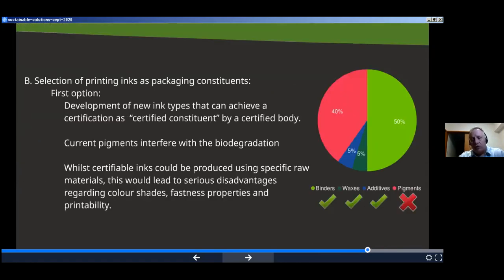One option is to change all the components of the ink to make them biodegradable. And here in this graph, you can see more or less the typical composition of the ink, where 50% of the ink is made of binder, which is a resin, typically. Then we have some waxes, additives, and then pigments. I told you before that the pigments are not biodegradable. So we can change these pigments into biodegradable pigments, like organic pigments, but we will never get the same color strength, the same light fastness, the same printing properties as current pigments. So it's quite difficult to make ink that will have the same performance as current inks and is also biodegradable.